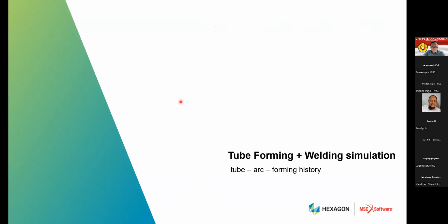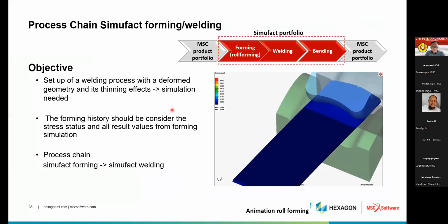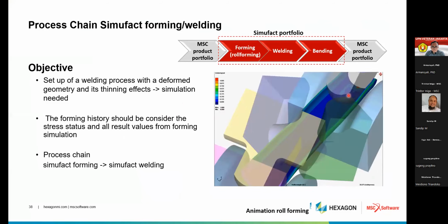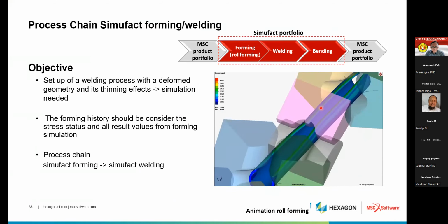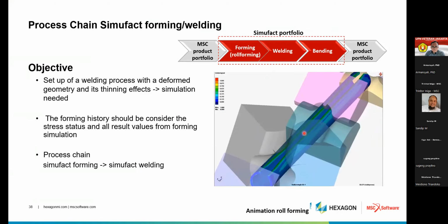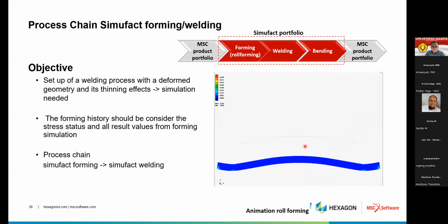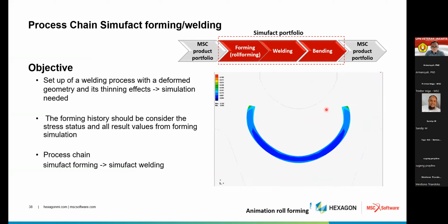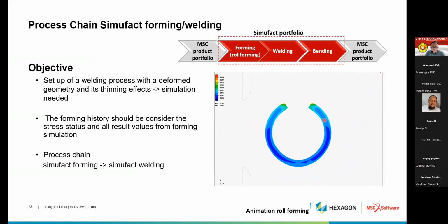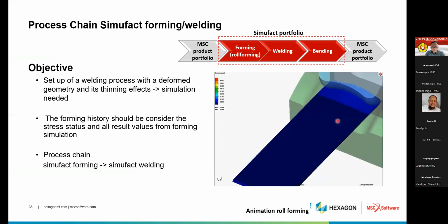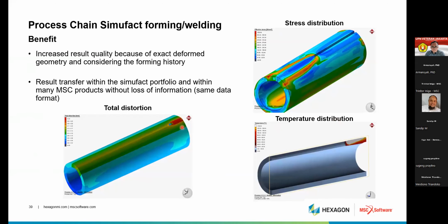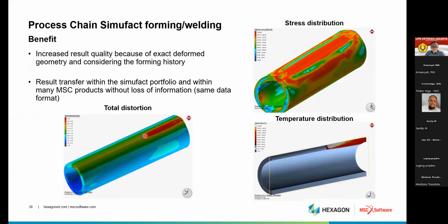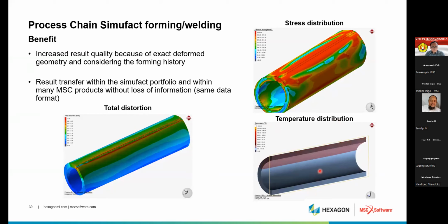Another example of the forming plus welding simulation is tube forming, where this flat sheet is passed to the roller. This is a rolling operation, and we can do it in Simufact forming. This is the cross section of it. You can see how the rolling operation is happening and creating a circular tube. Then we take it to the welding software, and we can see the welding operation happening over here. We can see the different results like distortion, stresses, and the temperature distribution.